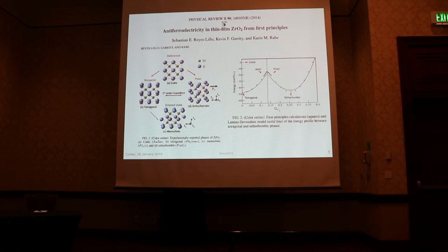So I mentioned several times this ground state structure is monoclinic. It has this structure, P2 sub 1 over c. And you can see already it's kind of hard to grasp what's going on even in this ground state structure. And then the polar structure is nothing like the polar structure that we think of in perovskites, where, for example, the long axis is the polar axis, and here the short axis is actually the polar axis. And if you just look at the picture, it's not so obvious why it's polar. I mean, there are displacements of the atoms that contribute to the polarization, but it's not something that just jumps out at you like it does in barium titanate or something like that.